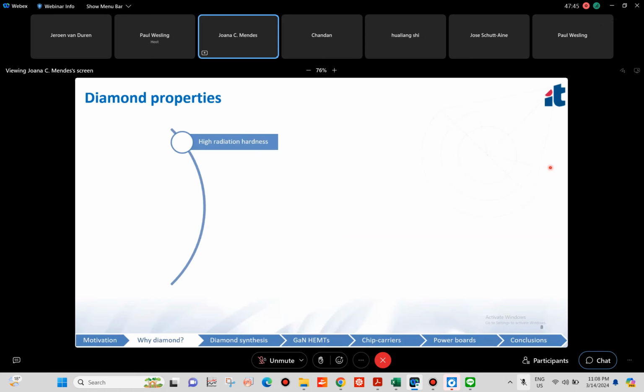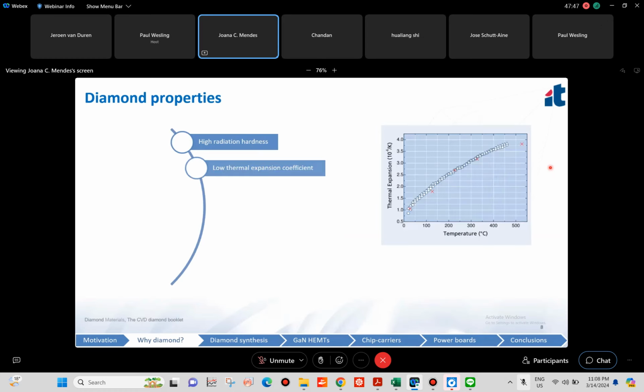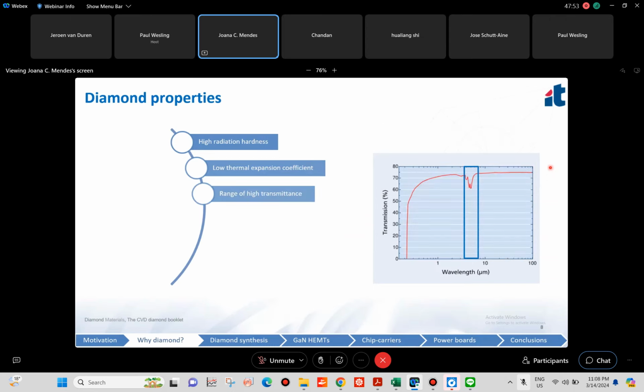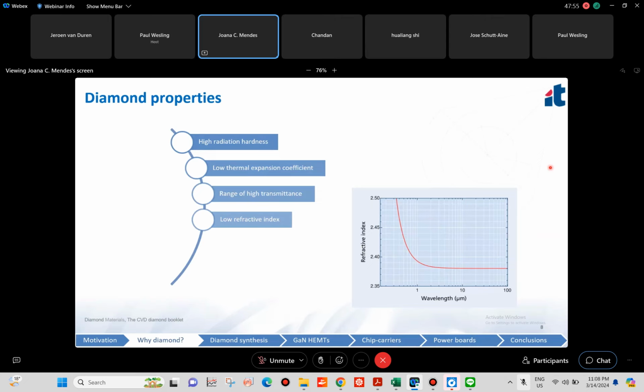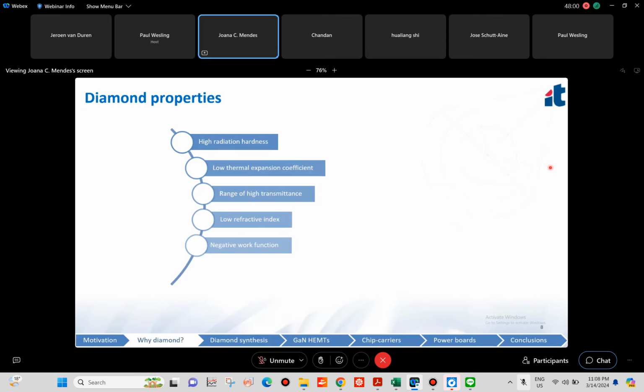In addition, it's radiation hard. It has a low thermal expansion coefficient, about 1 ppm per Kelvin. It's optically transparent, has a high refractive index of 2.38, and has a negative work function and is biocompatible. So it has a series of properties. Many of them are relevant for our particular application.